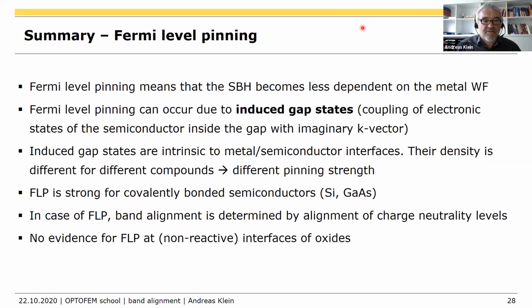All right, so that's the part on Fermi level pinning. Pinning means that the Schottky barrier height becomes less dependent on the metal work function. And it's an intrinsic property, these induced gap states. It doesn't need any crystallographic defects. They are intrinsic to that. But their density depends on the material.